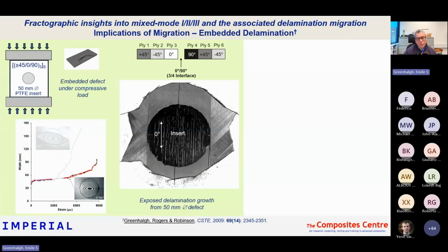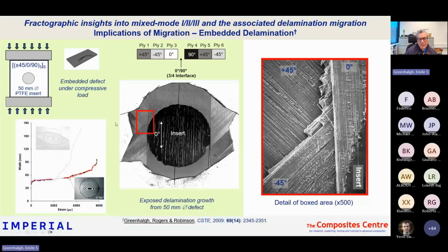Once we've done the test, we open that up. The delamination doesn't stay in the same interface as the original defect. It actually migrates through the layers. This is zooming in on this area shown in red. This is the 0 ply. This is the edge of that PTFE insert. And then these are the next ply interfaces. So what happens is that the crack jumps down through the layers because you're trying to force the crack to grow in a direction which is not in the direction of the fibers. And in order to propagate outward, it has to jump, it has to migrate through the layers. This really starts to invalidate this concept of cracks being self-similar in their growth. Early work assumed that if you grew a delamination in a composite laminate, it would stay in the original defect plane, and it doesn't.